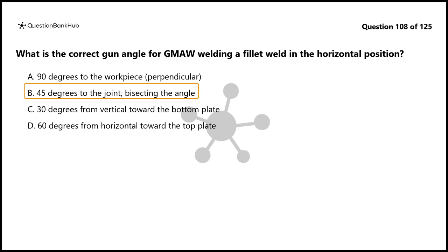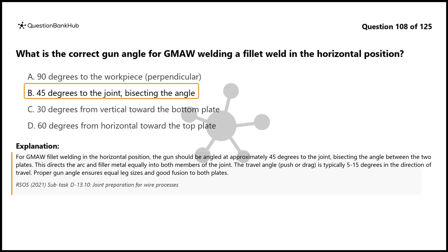The correct answer is B. 45 degrees to the joint, bisecting the angle. For GMAW fillet welding in the horizontal position, the gun should be angled at approximately 45 degrees to the joint, bisecting the angle between the two plates. This directs the arc and filler metal equally into both members of the joint. The travel angle, push or drag, is typically 5 to 15 degrees in the direction of travel. Proper gun angle ensures equal leg sizes and good fusion to both plates.